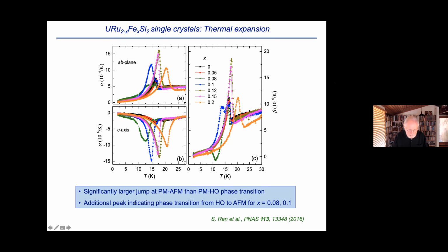And also there are some additional peaks that are kind of hard to pick out here, but they indicate the transition from the hidden order to the antiferromagnetic phase as you come down in temperature, because you first go from the paramagnetic to the hidden order phase. And then because this phase boundary is not vertical, you then go into the antiferromagnetic phase. So some of the complexity is due to that second transition.